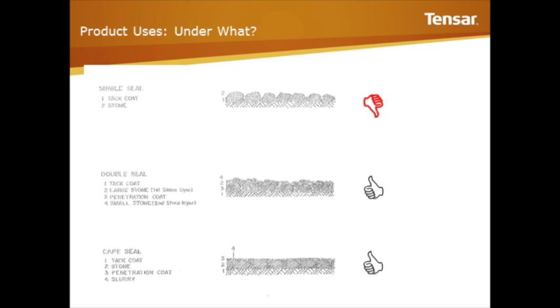And it goes back to that walking concept, and I'm sorry if that's an unusual concept that I'm referring to, but walking is typically the movement of particulate under traffic, so under braking, turning, acceleration. And a single chip, unfortunately, the aggregate is more likely to walk because it's not confined, whereas in a double chip you offer that stability. And that's why I say you could consider the use of interlayers underneath a double seal or a cape seal. And paving fabrics have traditionally been used for that. We would recommend a paving mat as a good alternative to that. And ultimately it's a pretty good insurance, increasing your binder content as a reservoir for your application, and also to protect your seal from cracks coming through.